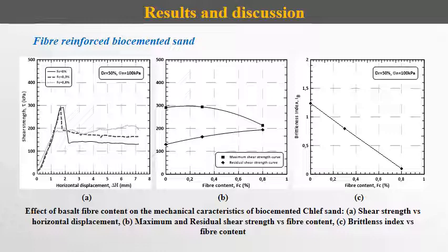From test results, it appears that the residual shear strength of test specimens increases with an increase of basalt fiber content. In addition, it is observed from figure C that fiber inclusion seems to have reduced the brittle behavior of biocemented sand specimens. The reduction of brittleness is more important at higher fiber contents.